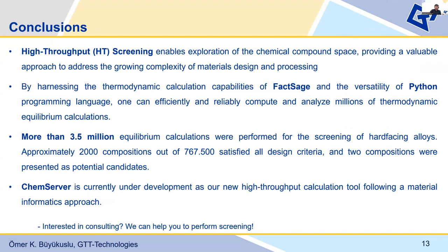As we saw, more than 3.5 million equilibrium calculations were performed for the screening of hard-facing alloys that I presented today. Approximately 2,000 compositions out of 767,500 satisfied all design criteria, and 2 compositions were presented as the potential candidates. Finally, the ChemServer is currently under development as our new high-throughput calculation tool. It follows a materials informatics approach.